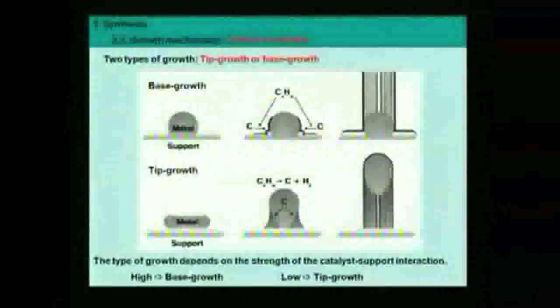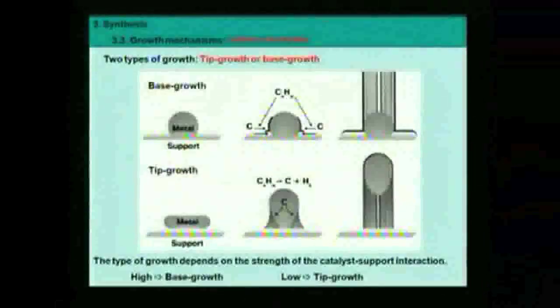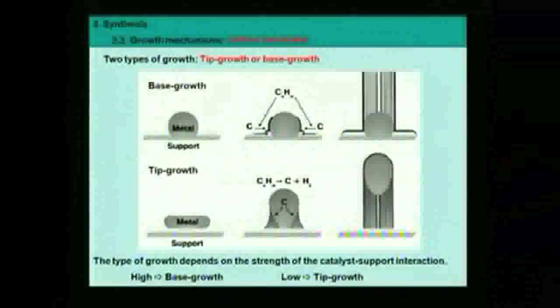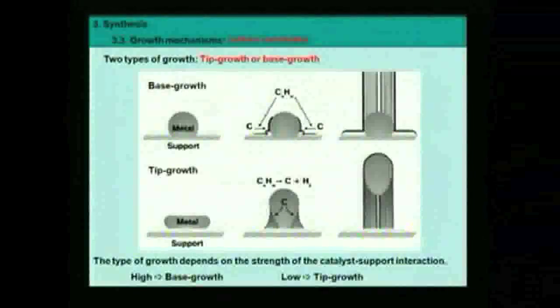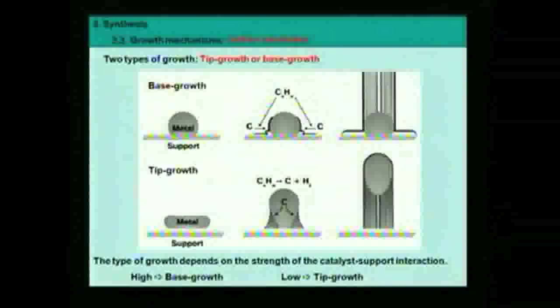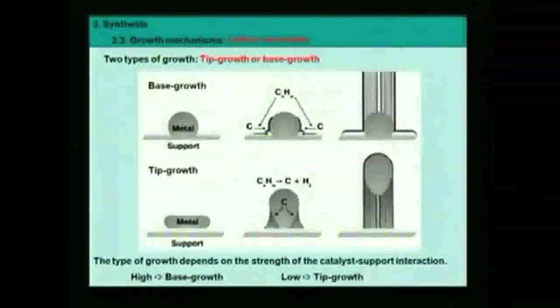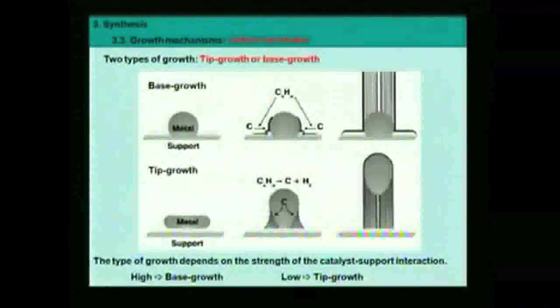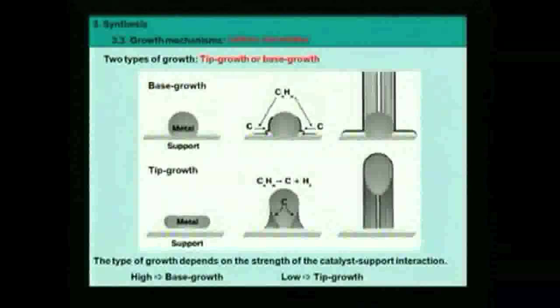The choice between those two types of growth depends on the interaction between the metal and the support. If the interaction is really strong, if the metal particle is well anchored to the substrate, then it will remain there and we have a base growth. On the contrary, if the interaction between graphite and the substrate is stronger than the interaction between the metal and the support, then we'll have a tip growth model like that. So it depends on this interaction.